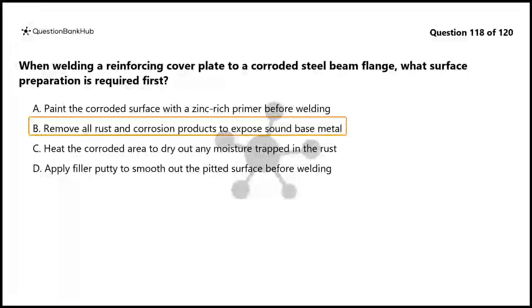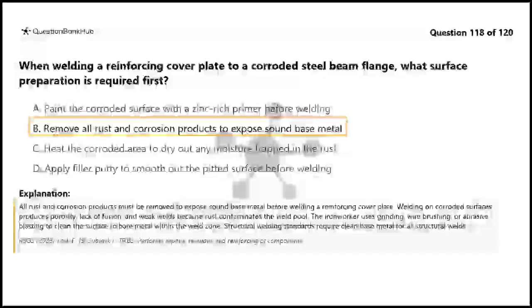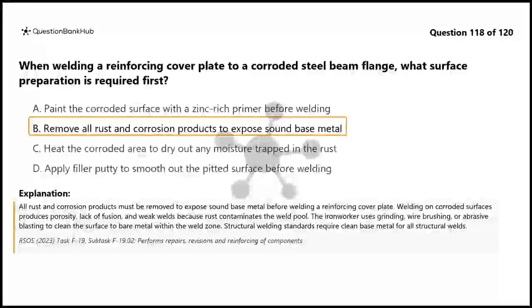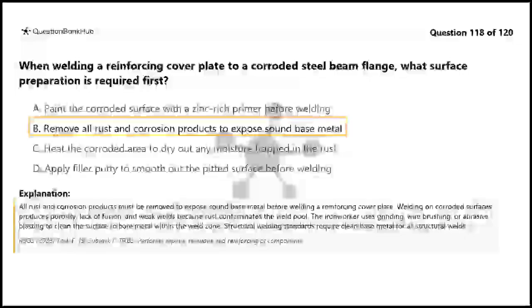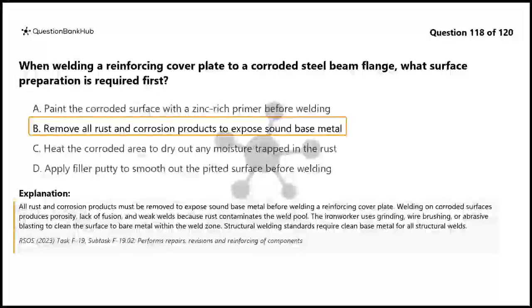The correct answer is B. Remove all rust and corrosion products to expose sound base metal. All rust and corrosion products must be removed to expose sound base metal before welding a reinforcing cover plate. Welding on corroded surfaces produces porosity, lack of fusion, and weak welds because rust contaminates the weld pool. The ironworker uses grinding, wire brushing, or abrasive blasting to clean the surface to bare metal within the weld zone. Structural welding standards require clean base metal for all structural welds.